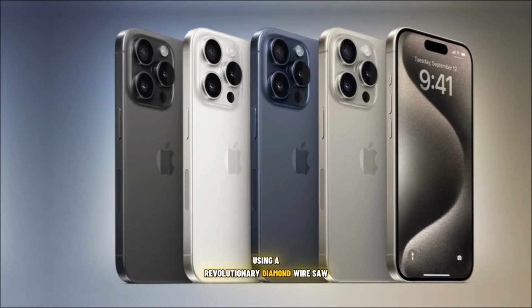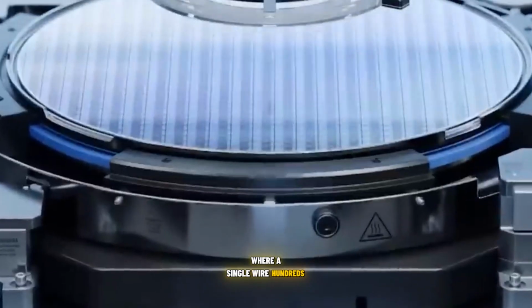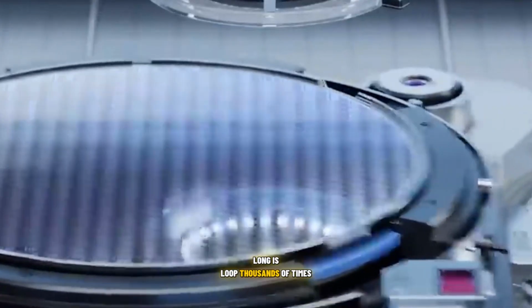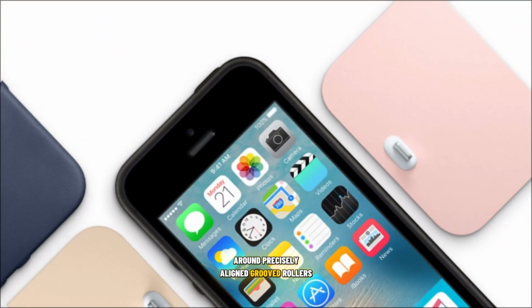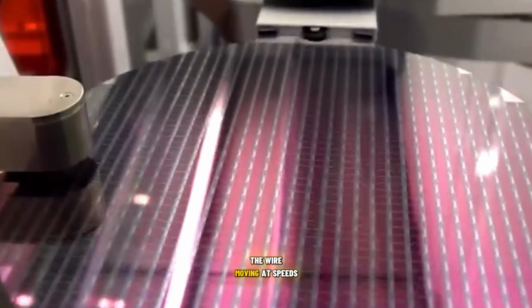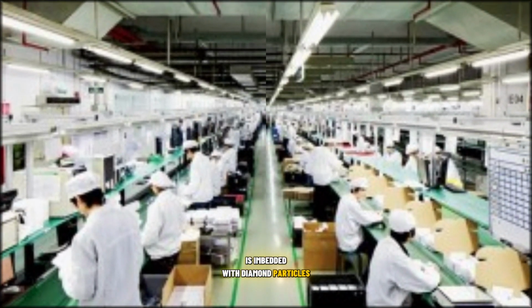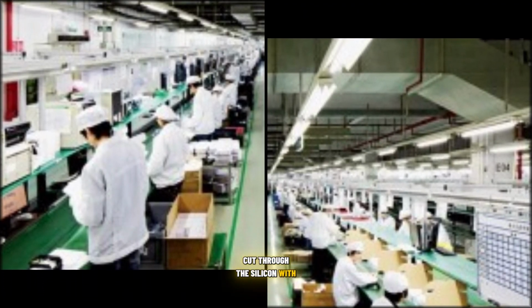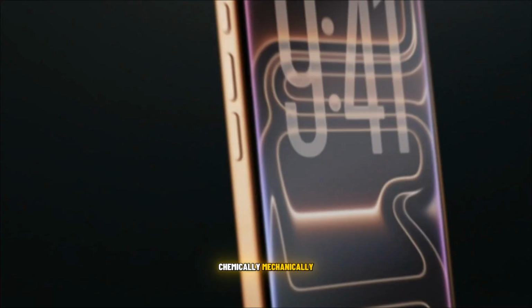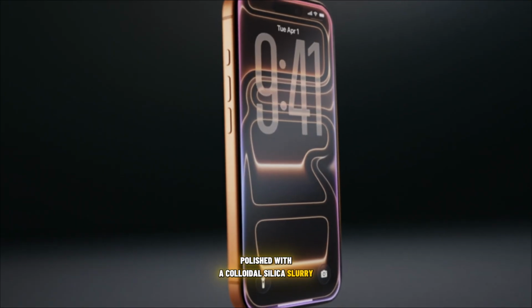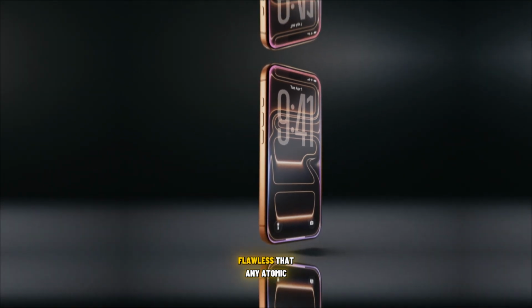Using a revolutionary diamond wire saw, where a single wire hundreds of kilometers long is looped thousands of times around precisely aligned grooved rollers, the ingot is sliced into wafers thinner than a credit card. The wire, moving at speeds over 60 kilometers per hour, is embedded with diamond particles that abrasively cut through the silicon with microscopic precision. The wafers are then lapped with a slurry of alumina particles to remove saw marks, and chemically mechanically polished with a colloidal silica slurry to achieve a surface so flawless that any atomic level irregularities are measured in angstroms.